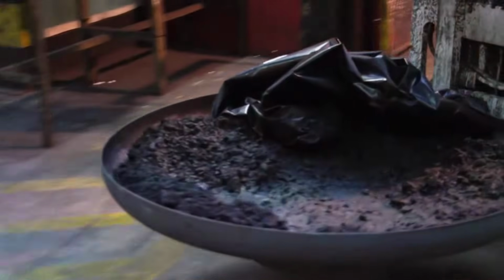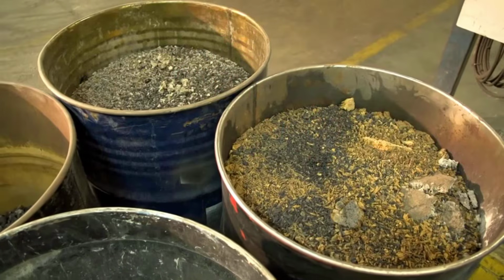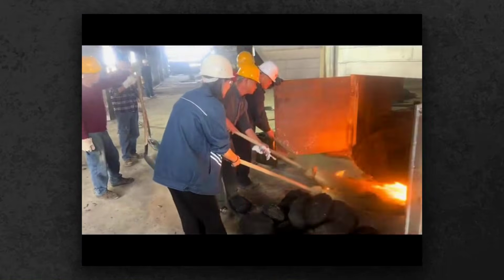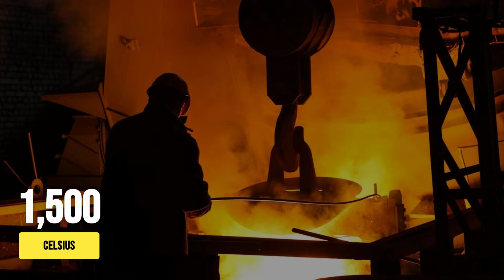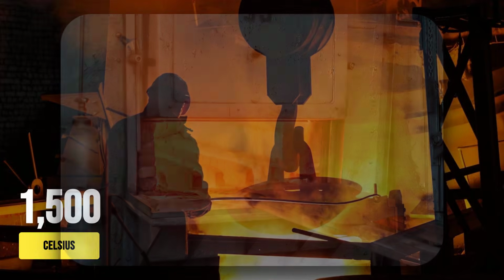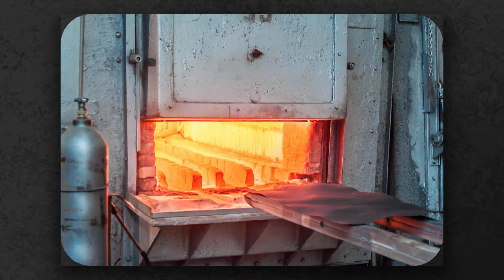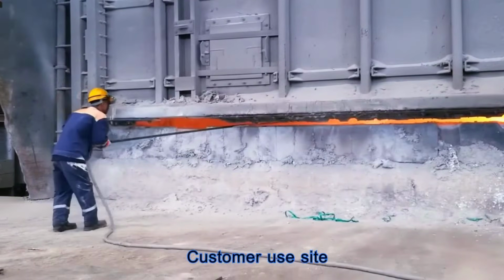Inside the smelter, heat reigns supreme. The concentrate, thick with platinum and other metals, is fed into a submerged electric arc furnace. Graphite electrodes, each as tall as a person, channel thousands of amps into the heart of the charge, pushing temperatures above 1,500 degrees Celsius, hotter than molten lava. Here, the ore transforms.